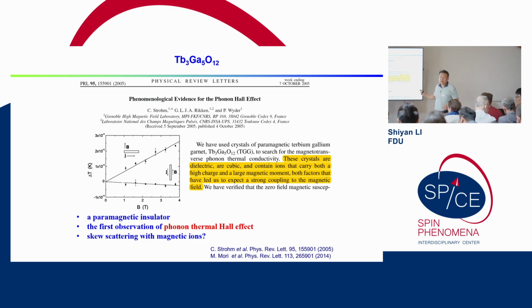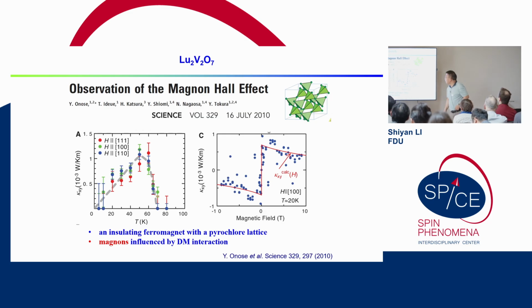But there were some following theoretical works suggesting maybe there is some skew scattering with the magnetic ions. Also, it has no magnetic order. Then in 2010, Professor Tokura's group observed the thermal Hall effect in an insulating ferromagnet, a 227 compound. The signal comes up below the magnetic order, and they attribute the signal to magnons, and they discuss some DM interaction.